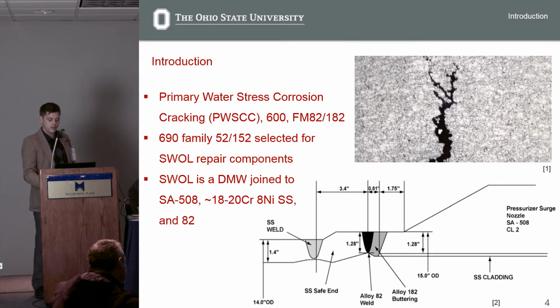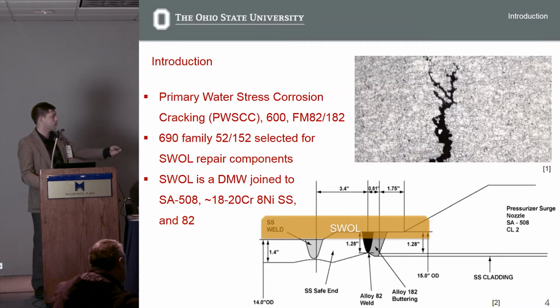So the chosen repair technique of the industry is to overlay structural weld overlay on top of this geometry that's a more developed alloy system of a higher chromium content to sort of halt this cracking propagation and provide an additional structural support to the surface of the weld.